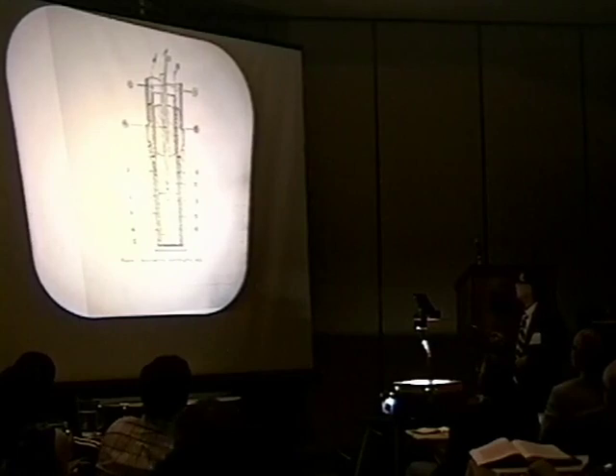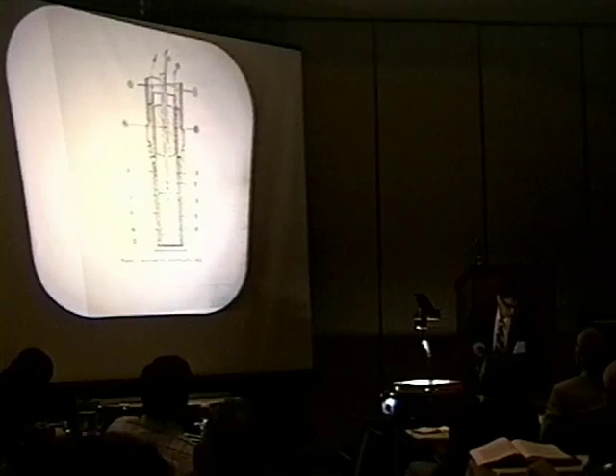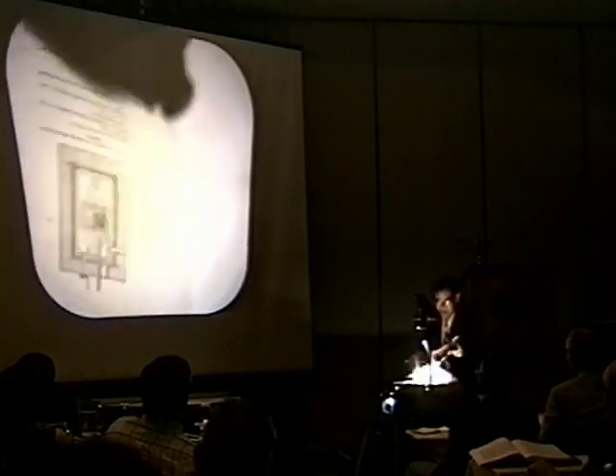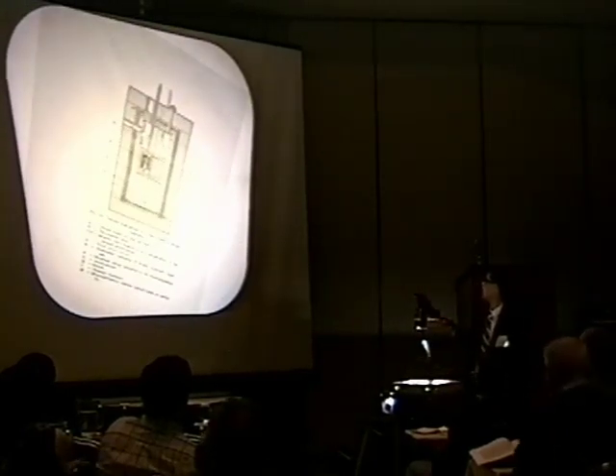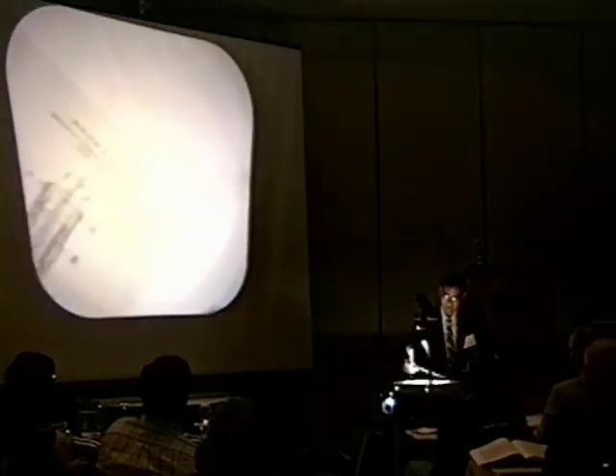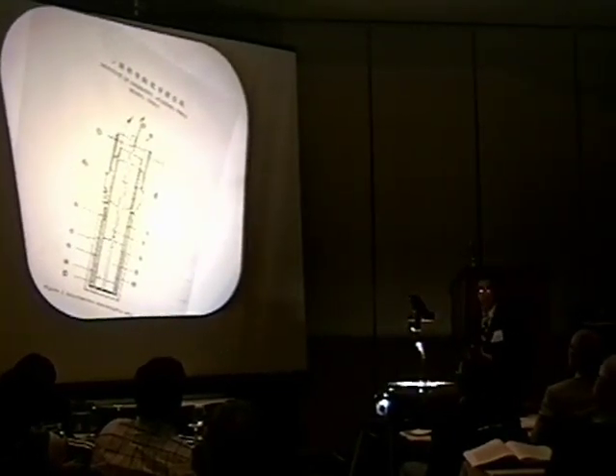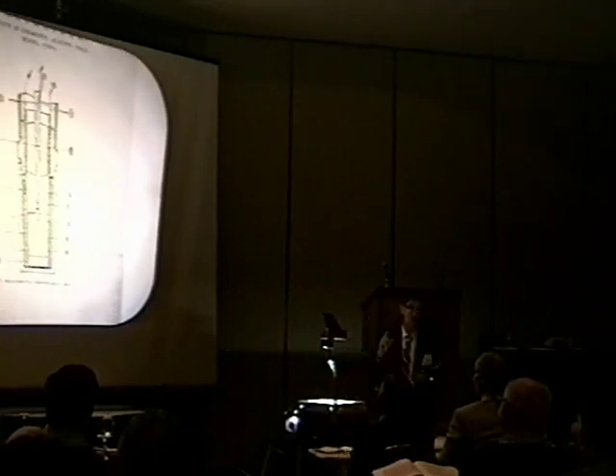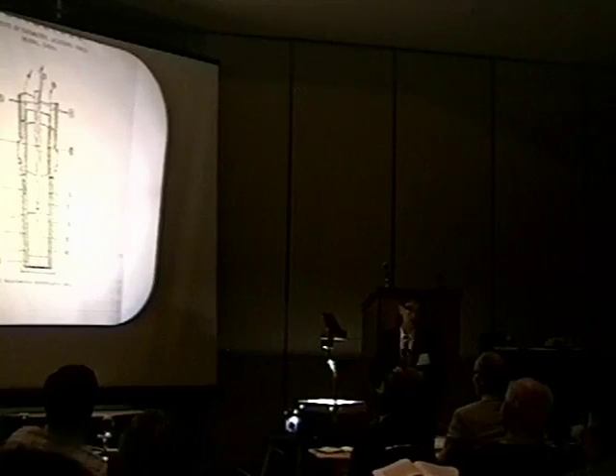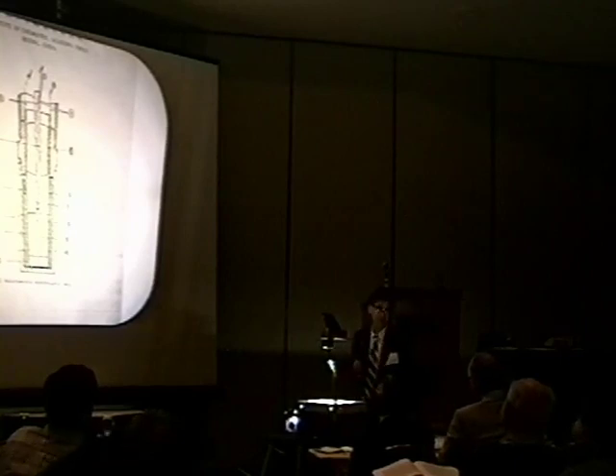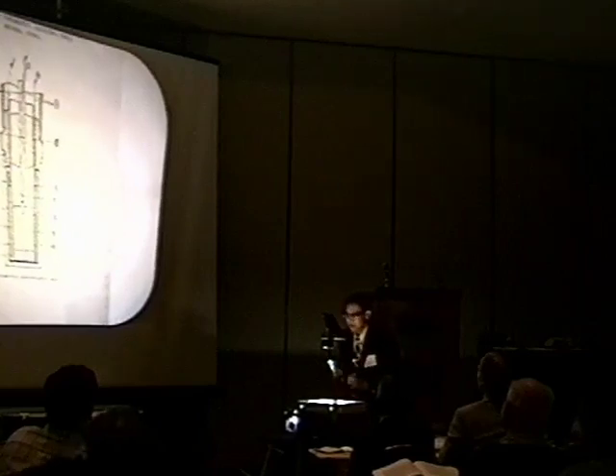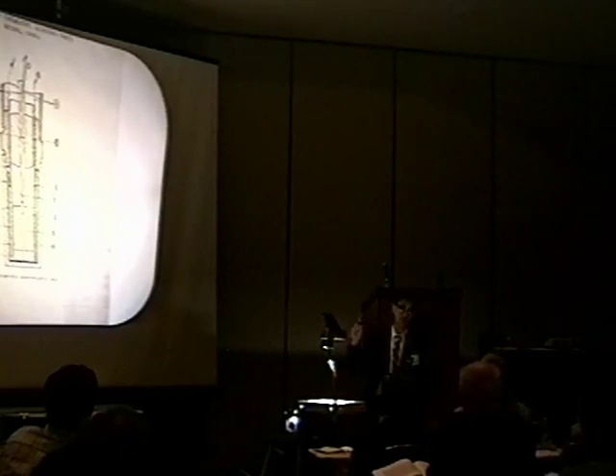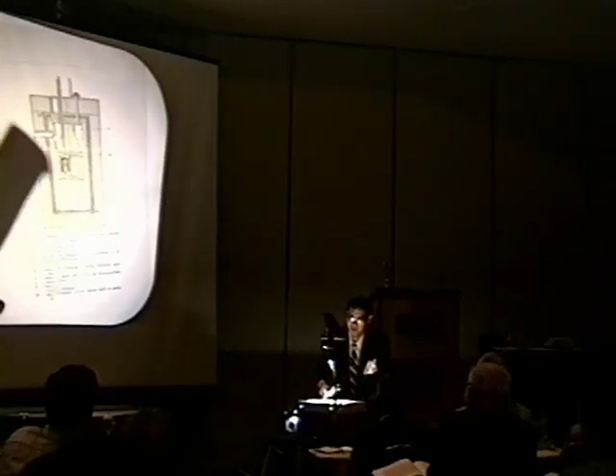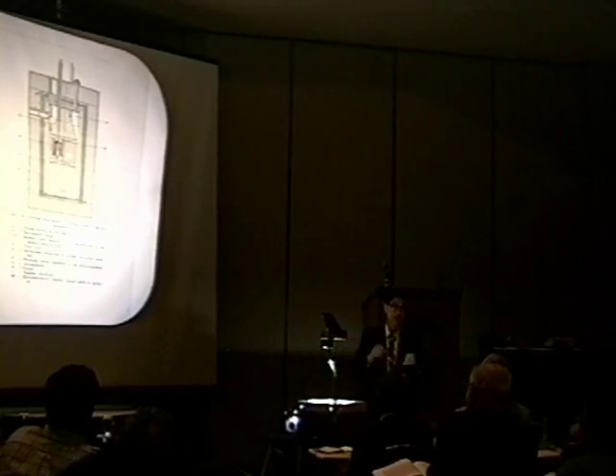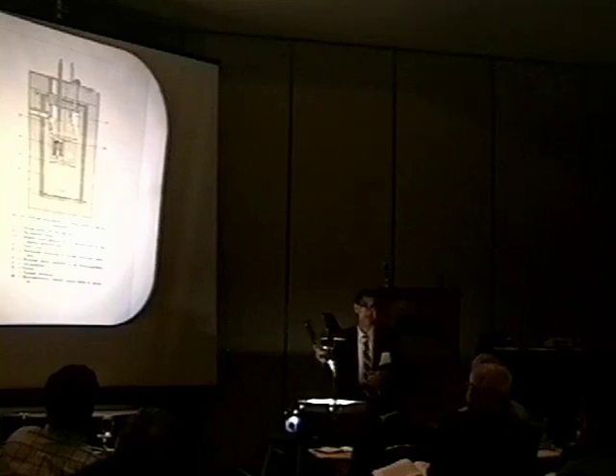We put this cell into the calorimeter here. And we use the constant current power supply for this experiment. We just monitor the cell voltage. We can monitor the power in. At the same time, we measure the voltage from the thermocouple. We can measure the heat generated in the calorimetric system here.